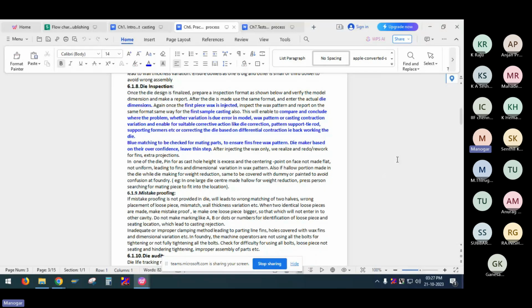Otherwise, this will lead to a line marking, which looks like a crack in the final casting, or extra fins which have to be filed or removed either in the fettling or in the wax assembly stage.